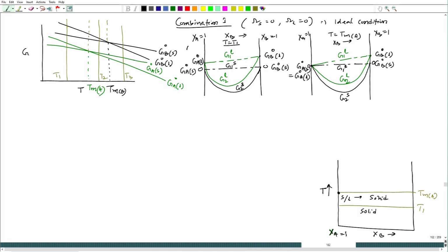And of course, this axis is the free energy axis. Now, let us plot at T equal to T2, and one more observation, please understand that you can draw it as per that. If we increase the temperature, we will see that the term minus T del S mix will go farther down and it will be steeper, convex downward.